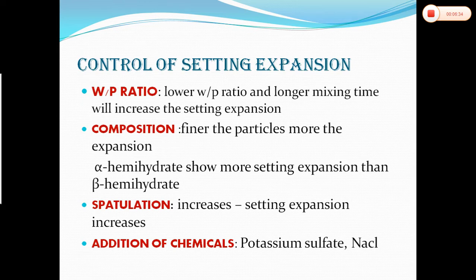And longer mixing time. We have seen during hand spatulation, as the crystals are growing, because of our spatulation, one crystal will be broken into more crystals. So more breakdown happens, and more nuclei of crystals will be present. More crystals, more expansion. You can see lower water powder ratio and longer mixing time will increase the setting expansion. And also composition: the finer the particles, the more the expansion. Finer particles will dissolve easily, so crystals will form easily and more expansion happens.